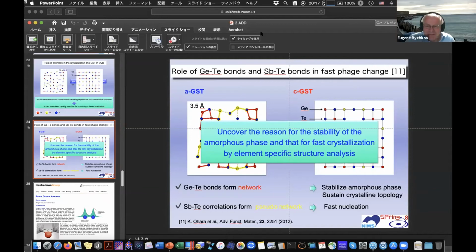I have a comment about it. The biggest first sharp diffraction peak is in molecular liquids, where in principle the position of the peak is proportional to the average intermolecular distance. If you just take the value of the FSDP in Q space and divide 2 pi by Q, you will get roughly the intermolecular distance, which you could find quite easily.